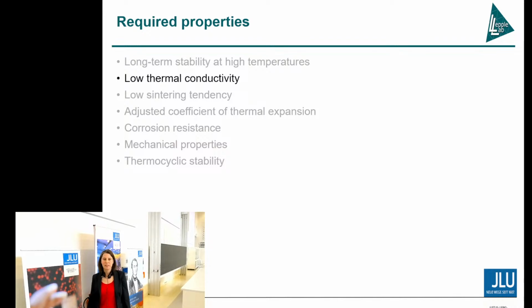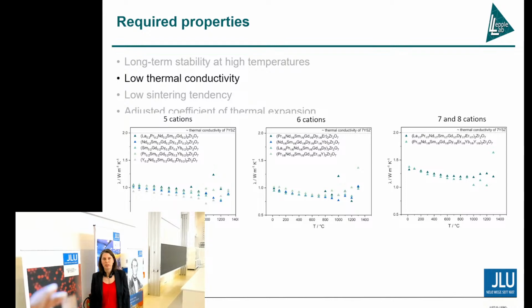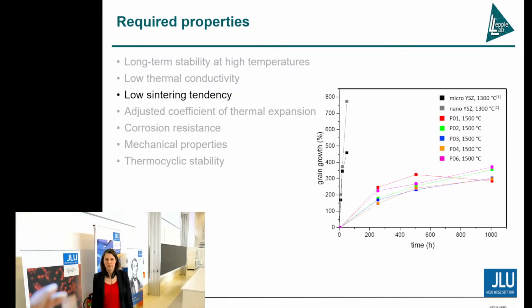Then looking at the low thermal conductivity, we actually achieved thermal conductivities way below the currently state-of-the-art material, which is 7 YSZ, so yttria stabilized zirconia. You can see the benchmark value of approximately 2 plotted with a dashed line, and the values of the high entropy oxides are below 1, which is a high decrease. When we look at the low sintering tendency, here we can see the high entropy oxides compared to the yttria stabilized zirconia. We heat treated the high entropy oxides even at higher temperature than the yttria stabilized zirconia, and we see that the sintering tendency is much lower.